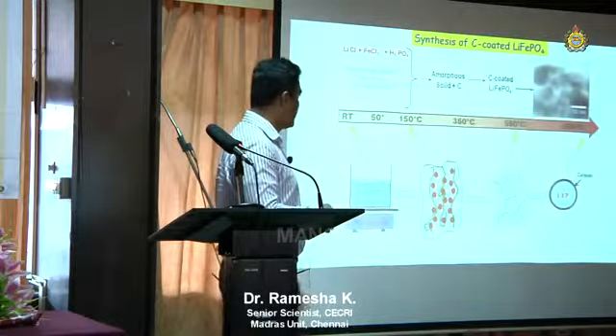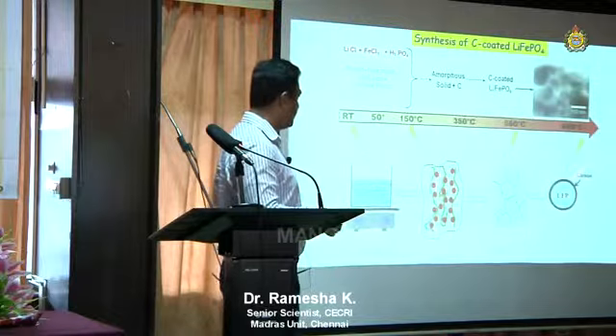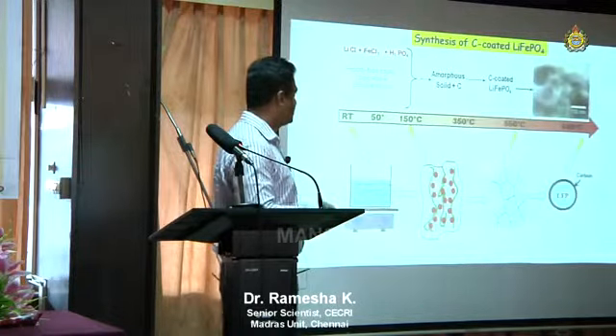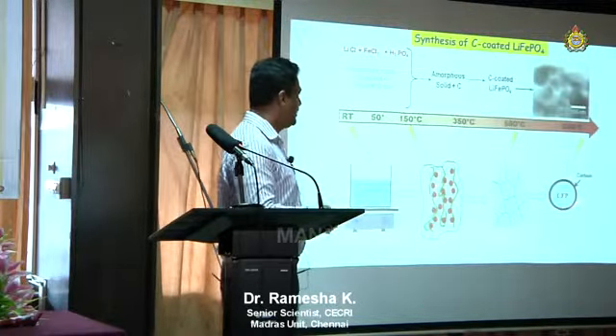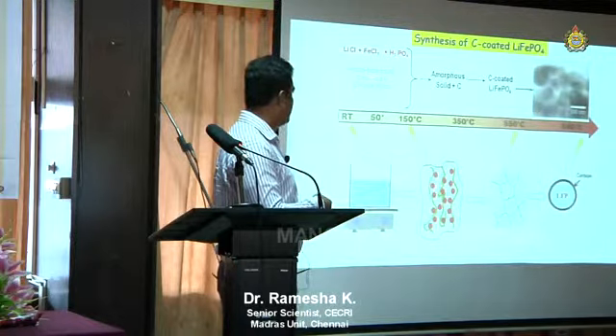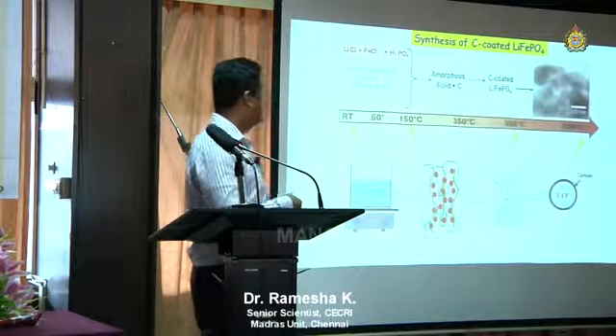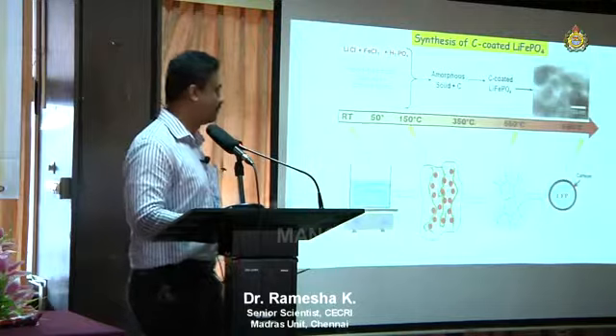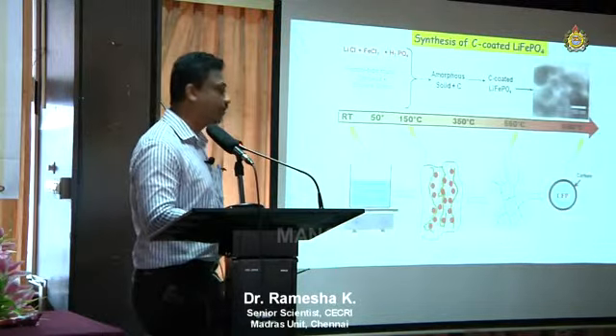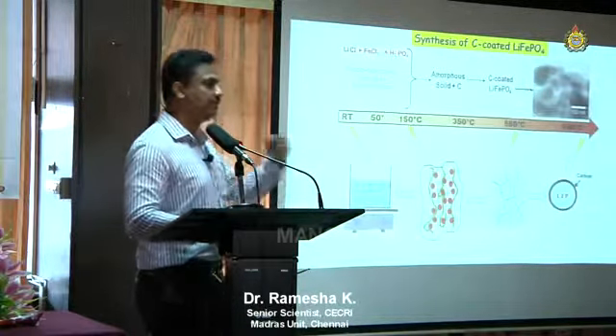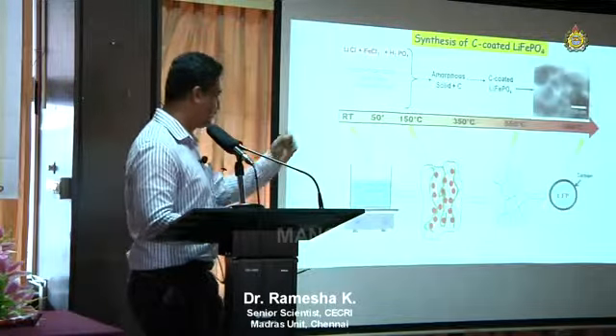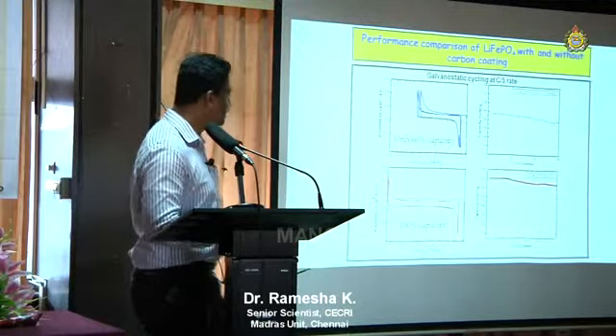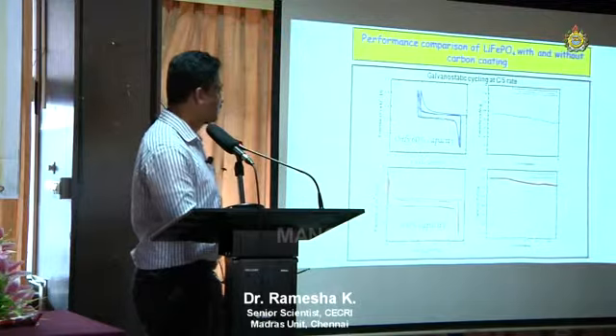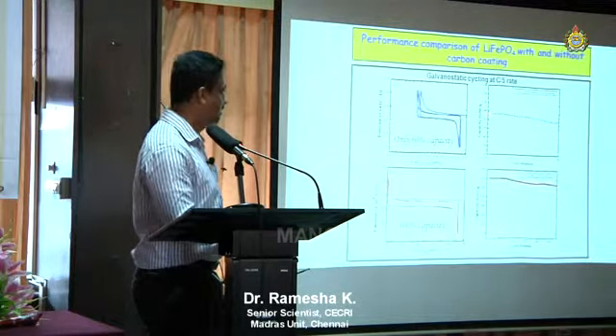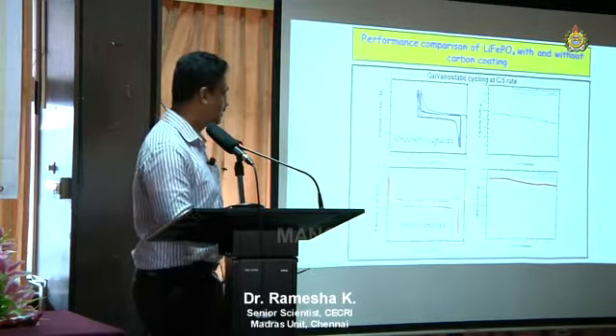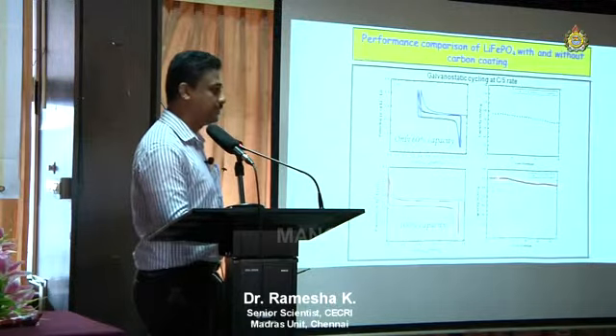We made nanoparticles of lithium iron phosphate by a simple technique. Since we use ethylene glycol, citric acid, all these things, finally it makes a carbon coating around these particles, a very thin coating, just a few nanometers. Then you see that without that your capacity is very low, less than 100. When you do the coating around, you can get the theoretical 160.